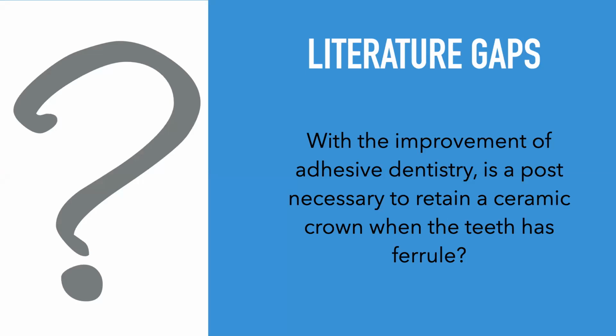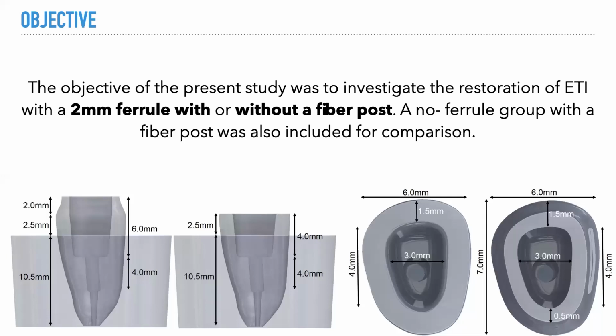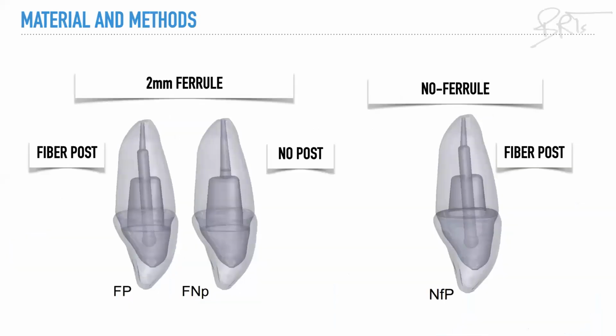in endodontically treated incisors? So the objective of this first study was to investigate the restoration of endodontically treated incisors with 2 millimeters of ferrule with and without fiber posts. And we used a non-ferrule group with fiber posts also for comparison. So here we have our 3 groups from this first study. 2 of the groups with 2 millimeters ferrule and 1 of them with no ferrule. Of the 2 millimeter groups, 1 of them received a glass fiber post, and another one was restored without posts.